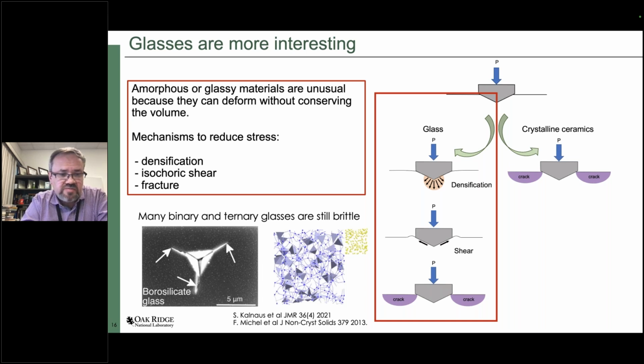This is the typical example of what happens in borosilicate glass when you apply nanoindentation to it. And the reason for that is very simple, because most of the commercial glasses are highly networked, meaning that the tetrahedra are typically connected into this highly networked structure, which constrains the structure to the point that it prefers cracking as opposed to flowing in shear. They can densify, but flow in shear is a little bit more tricky.